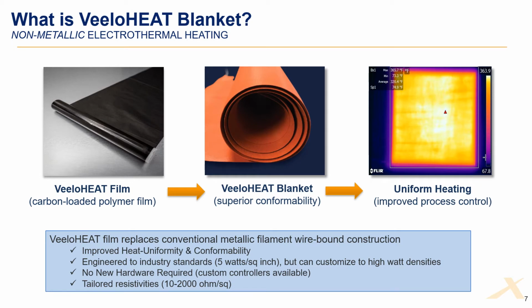Typically, this is at 5 watts per square inch power density. Next, the film is integrated into off-the-shelf silicone film. Because of this continuous nature of the heater film, we're able to achieve a very high uniformity in the heat profile in the final product.